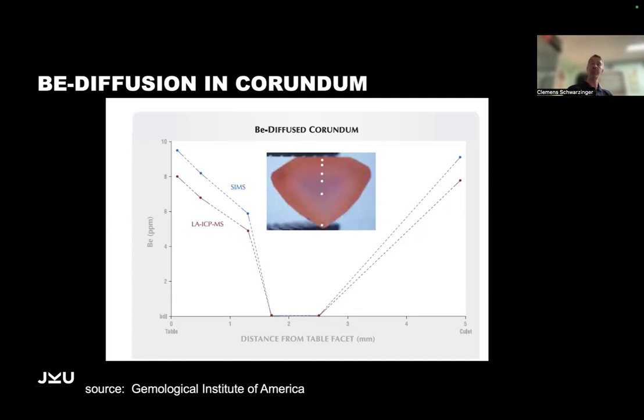So what happens is that the beryllium, which is a very small element, is small enough to diffuse into the crystal, into the cut gem, and goes down a millimeter, maybe 1.5 millimeters. And then it produces, due to a complex mechanism, this orange color. This is extremely hard to detect, because when people were looking at chemical data, they were usually using microprobe or X-ray techniques, and they're blind to beryllium because it is just too small. It was only possible by, for example, slicing a corundum crystal and seeing that the core has a different color than the rim, then it's obviously a diffusion from the outside towards the inside.